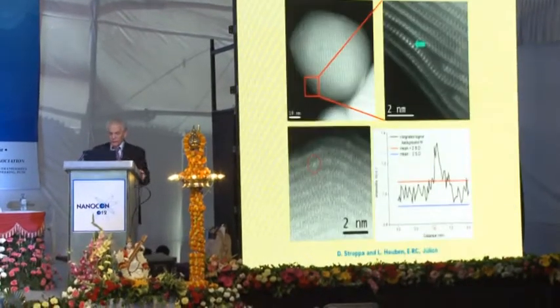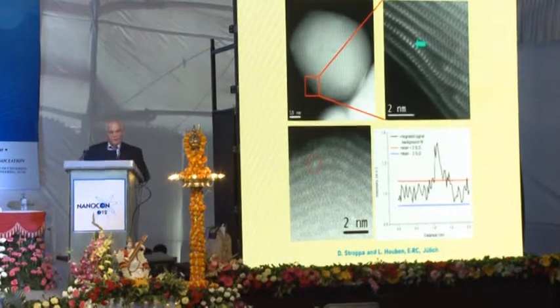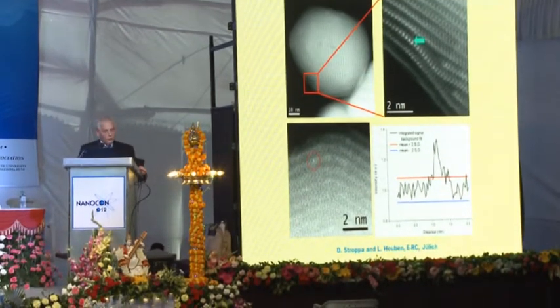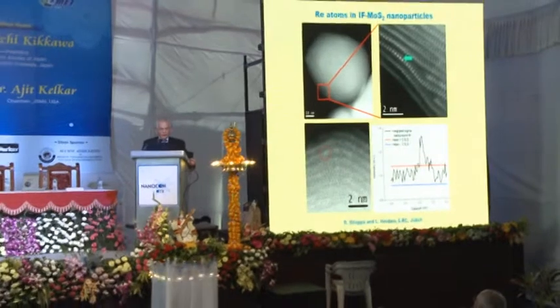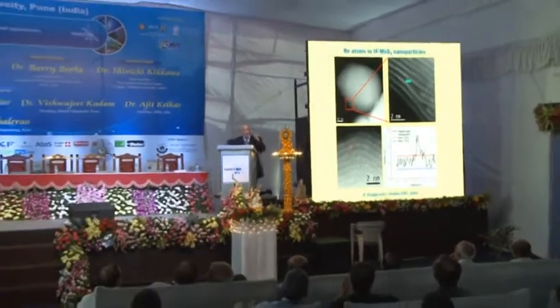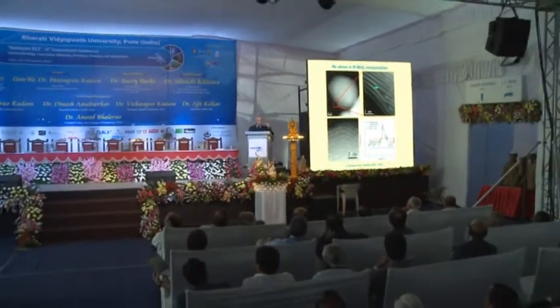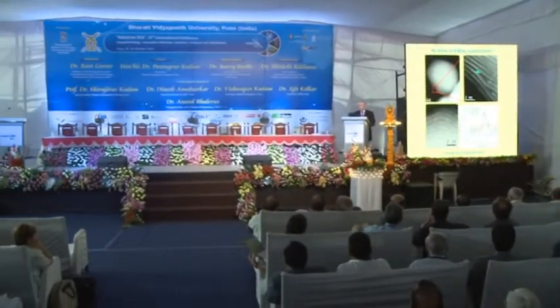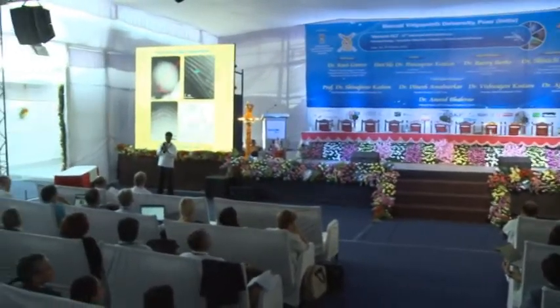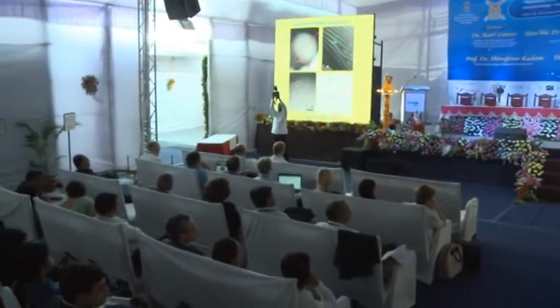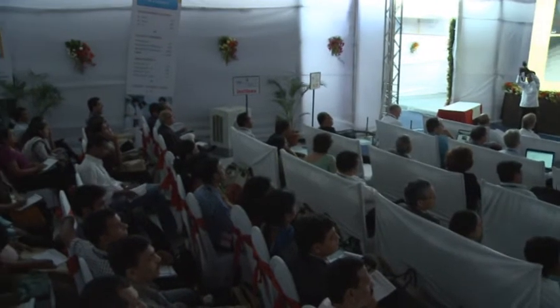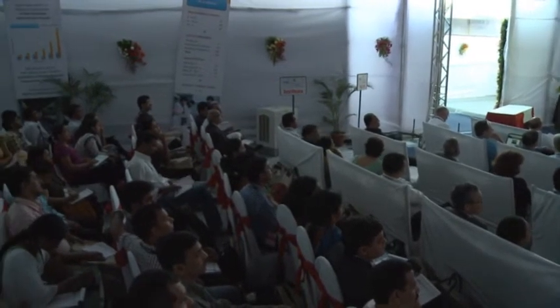And I won't show it for the lack of time. I probably will finish here by showing you 1 or 2 more slides. And this is the rhenium doping. I told you that we had a very good lubricant, but we had an idea to improve this lubrication behavior even further. In order to achieve that, we learned to synthesize nanoparticles or nanotubes which are doped with rhenium atoms. The reason for doping with rhenium atoms is that rhenium sits to the right of molybdenum and tungsten and consequently has 1 extra electron.